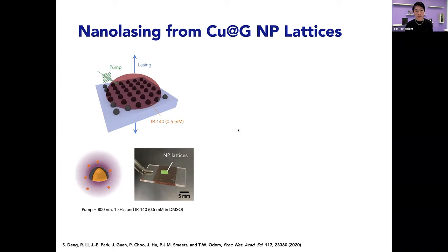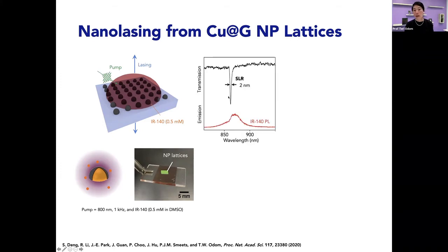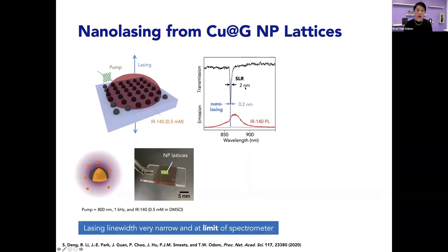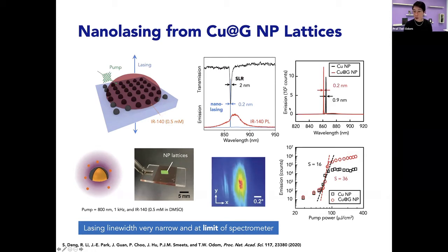It looks quite nice. We start off with the cavity mode, which is a very high quality. It's already 2 nanometers full width half max. And then we are able to achieve lasing at this SLR wavelength. And the lasing line width is less than 0.2 nanometers. I expect it is actually less than this, but that's just the limit of the spectrometer, which is pretty nice. It comes off as a beam and as a spot, and there's a slight difference in the nonlinear thresholds of whether it's just copper or whether there's graphene around copper. But in general, it's a very nice system.